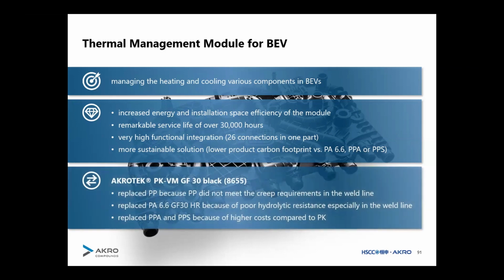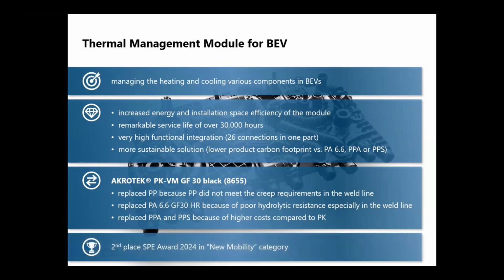So yeah, we use here a 30% glass fiber reinforced polyketone, and in the beginning the idea was to make it in polypropylene, but it simply did not work because of creep. And with all these many weld lines over the long time with temperature, you also get leakage when using a nylon 6,6 glass fiber reinforced. PPA and PPS would most likely work, but it's simply more expensive. So you go for the polyketone solution.